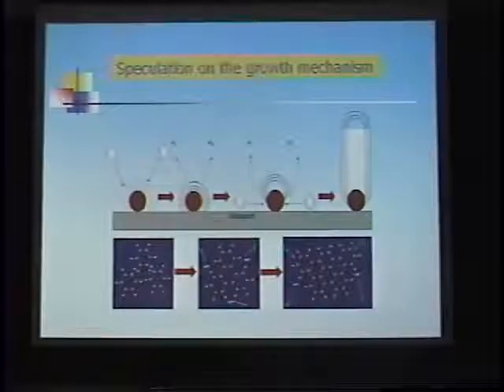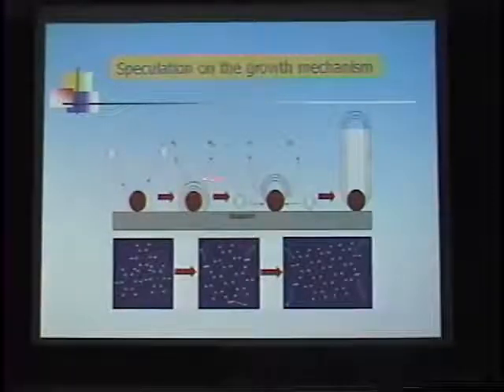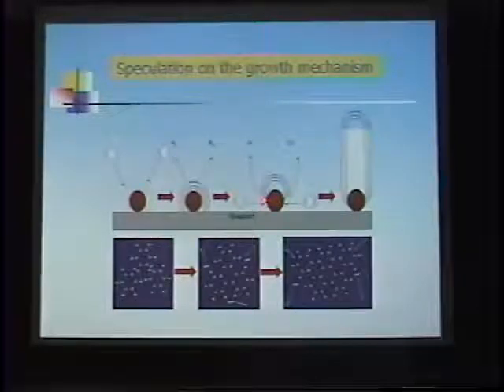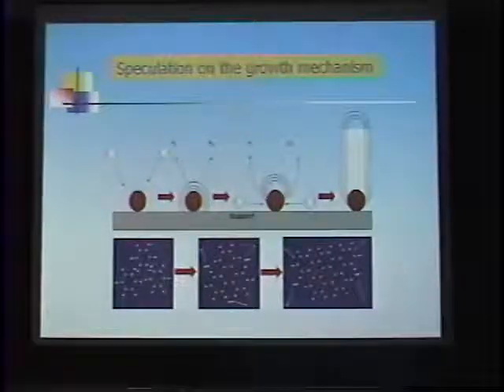So then the graphene sheet covers the catalyst surface, and due to the increase of the strain energy, it will precipitate into a tubular structure, and further incorporation of benzene molecules at the edge will result in the growth of carbon nanotubes. Finally, a carbon nanotube will be obtained. And is this the real story?